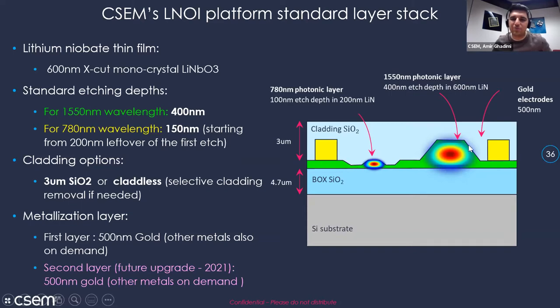So you can either make your PIC in this 1550 layer, or in the other one. In terms of gold, we have 500 nanometers of gold as electrodes and 3 micron of SiO2 cladding, but we offer to remove the cladding locally, either on top of the electrodes to access them or on top of the waveguides. Some of our clients came to us needing a particular dispersion relationship in a waveguide or resonator, and when we simulated it, if you don't have a cladding, you can achieve that.